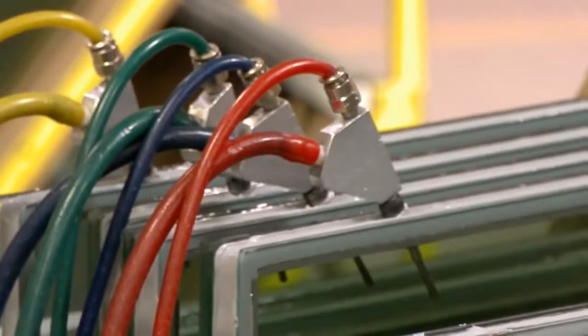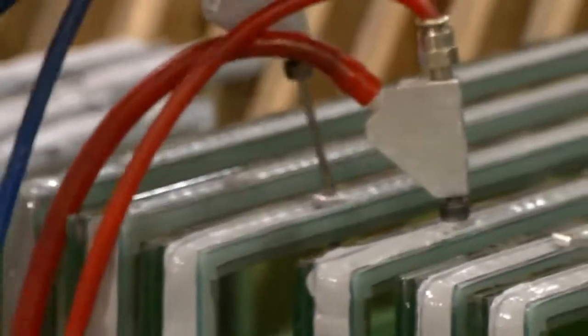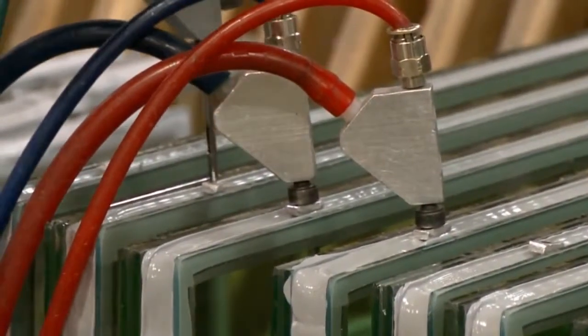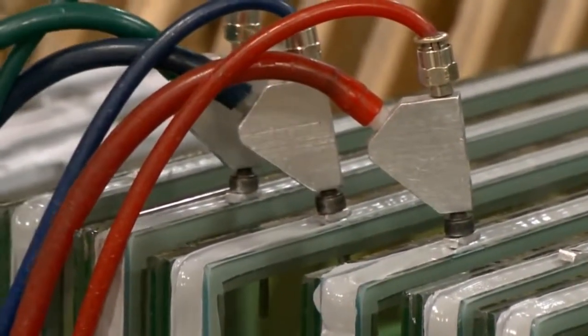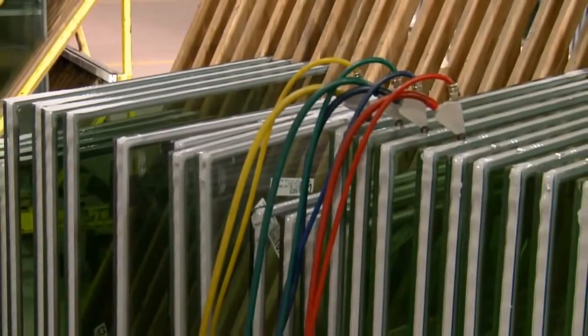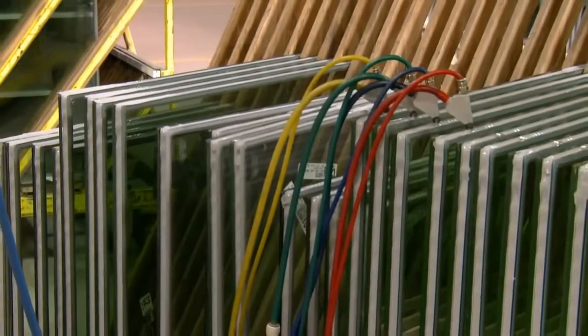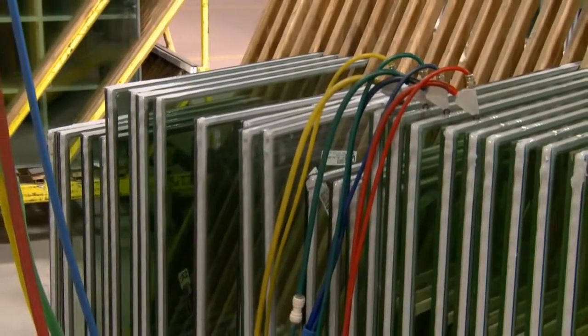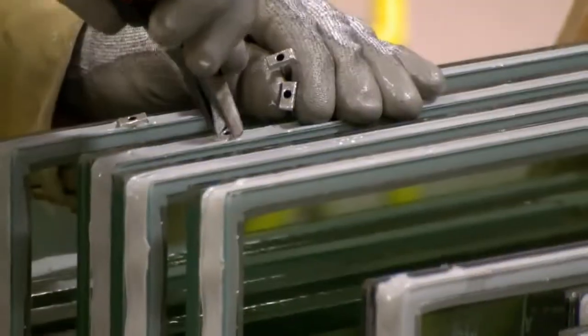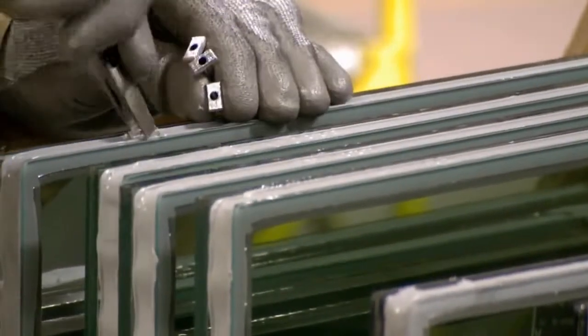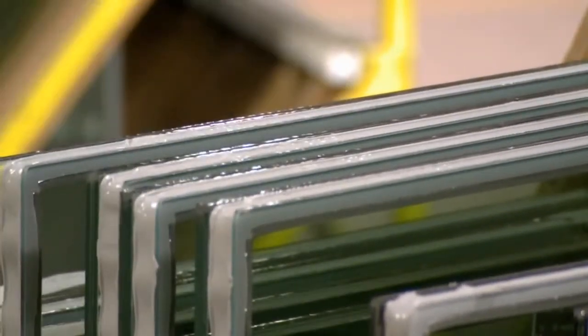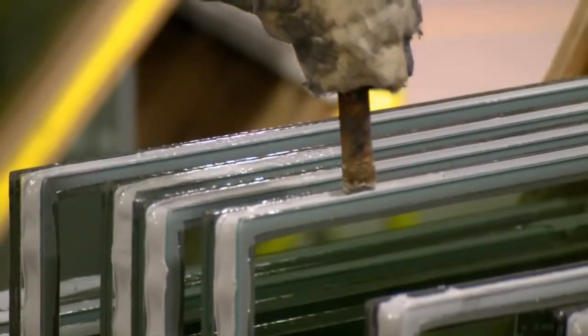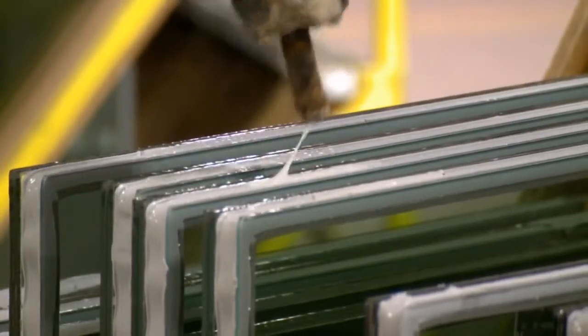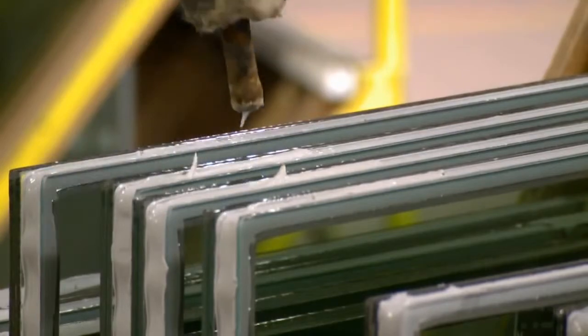Here we see argon gas being inserted and sealed into some IG units. Argon gas is an odorless, non-toxic gas that is much denser than air, and it is an excellent insulator. This process not only inserts argon gas, it also draws out air from the IG unit and analyzes the makeup of that air. This analysis ensures that we are inserting the optimum mixture of argon and air. After the optimum mixture is transferred into the units, it is sealed off with butyl.